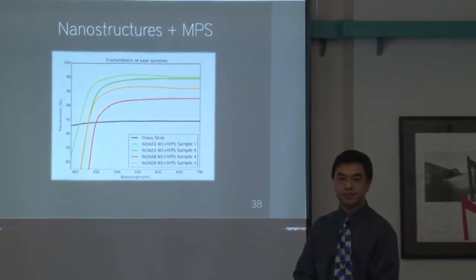The height of the polymer is based off the black silicon master mold. [Question: How do you measure the combined mesoporous silica and nanostructure thickness together?] The thickness of the mesoporous silica alone was measured using Dektak — we scratch the MPS layer and measure the difference. However, if we scratch the nanostructures, we'd destroy both the MPS and the nanostructures, so we don't know where Dektak would start measuring. We therefore inferred the film thickness from measurements made on blank glass substrates with the same deposition conditions.